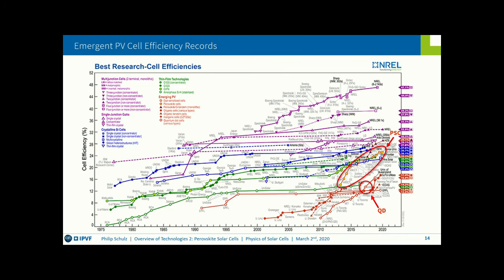And then also on this view graph, you can see that the quantum dots are here, and starting from this point over here, we now also have halide perovskites permeating this axis and taking over the quantum dot solar cell world. Also very interesting, the organic solar cells have been abandoned more or less, but they have made a comeback. So they were tanking at 12, 12 point something percent for quite a while, and now we reach efficiencies of over 17% power conversion efficiency. Key point here is that you substitute your typical acceptor molecule, which was a C60 molecule, by new small molecule acceptors that do a better job.